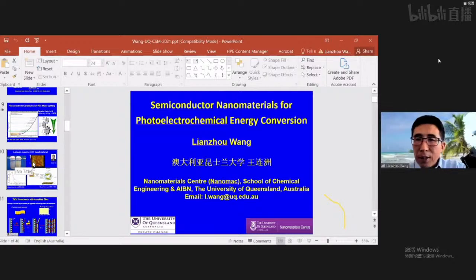Yeah, okay, thanks. I think this is, again, another very important question. Of course, oxygen vacancy sometimes is pretty difficult to control. Whether it's on the surface or in the bulk, during the reaction process, it can be not stable in some way. So you really need to have very good control of this approach. If you have too much oxygen vacancy, certainly you will damage the performance of the PEC system.